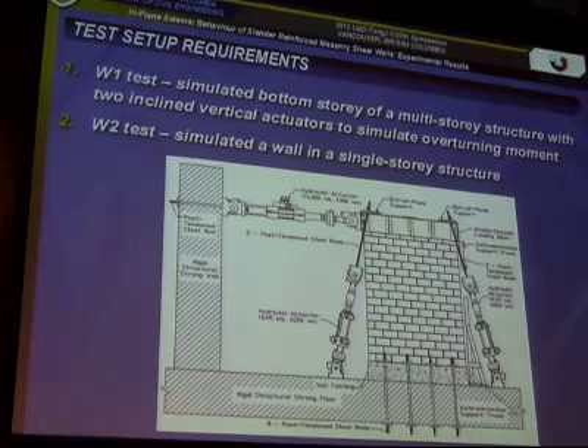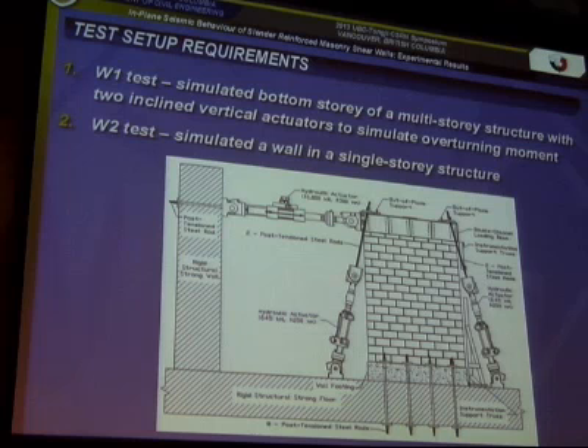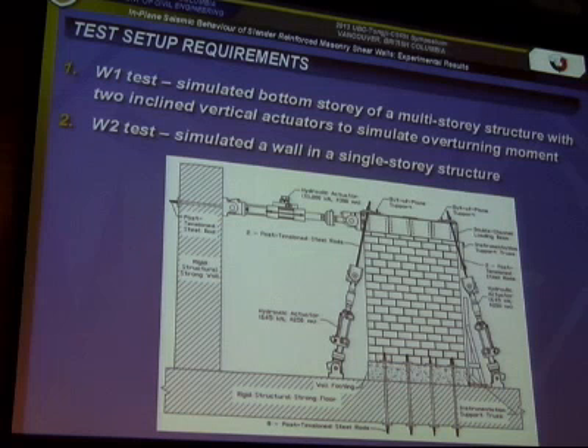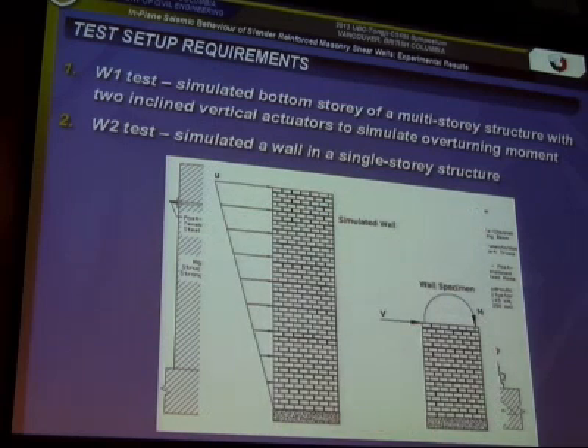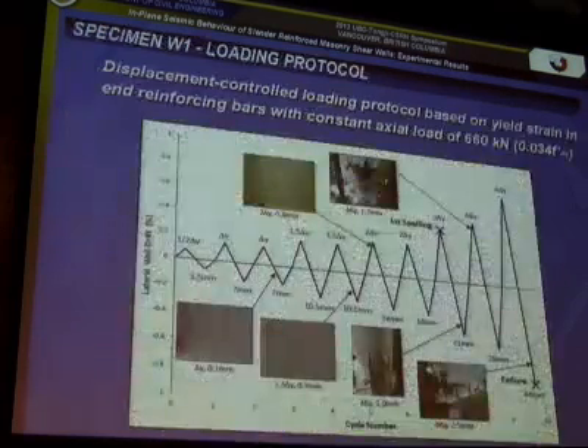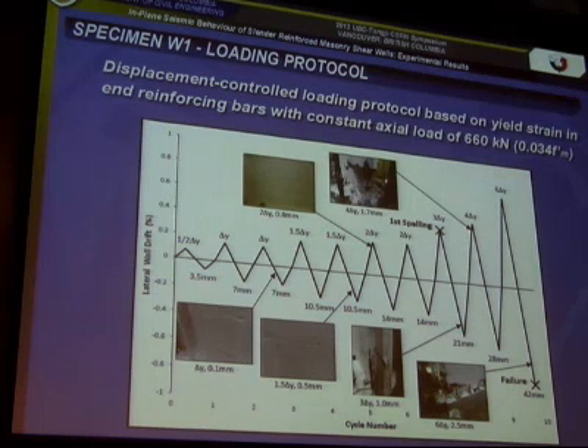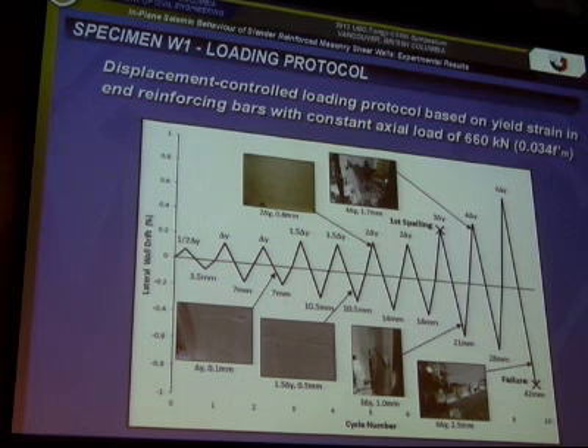So there were two types of tests done on these walls. The first test was meant to simulate the bottom story of a multi-story structure, so it required the use of 3 actuators, with the 2 vertical actuators representing both the axial loads and the overturning moment from the stories above. And the second wall represented only a single-story structure, say a warehouse, and did not require the use of these 2 vertical actuators. So the loading protocol was displacement-based and used a displacement increment which had its basis in the lateral displacement causing reinforcement yielding in the most exterior bars. And all this was with a constant axial load of 660 kilonewtons.